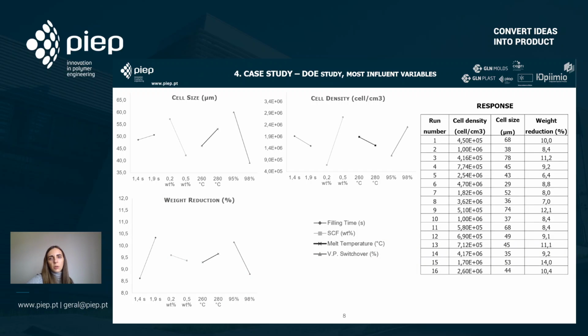Having conducted this DoE, we then study the most influent parameters as a result of the responses we obtained. The responses are presented here on the table on the right, and from the influence graphs, we can see that for cell size and cell density, we will have inverse responses. For lower cell sizes, which is what we want, we would have to incorporate 0.5 amount of the gas, which is one of the most influent parameters, and fill the cavity to 98% with the velocity point switchover, which is another of the most influent parameters.